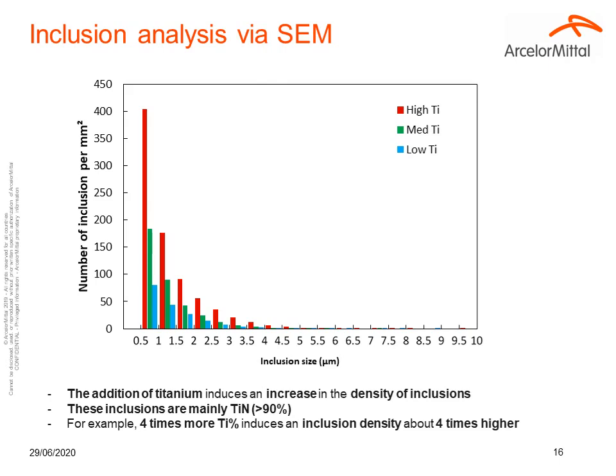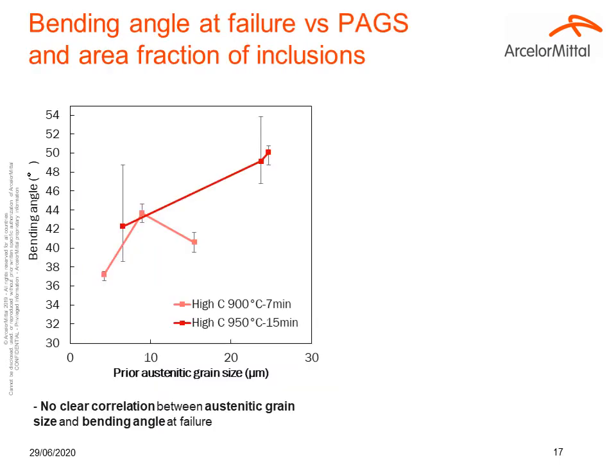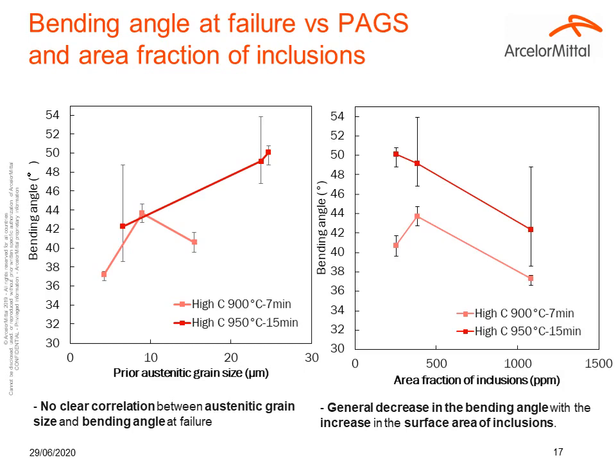So what are the effects on bendability? This inclusion population comes together with a difference in grain size, and here you have the bending angle at failure versus the prior austenite grain size. Despite coarse grain size, superior bending angles are achieved, and when we look closer at the inclusion population, we can observe that the high area fraction of titanium nitride seems to be detrimental to the bending performance. A general decrease in the bending angle with the increase in the surface area of inclusions can be observed.